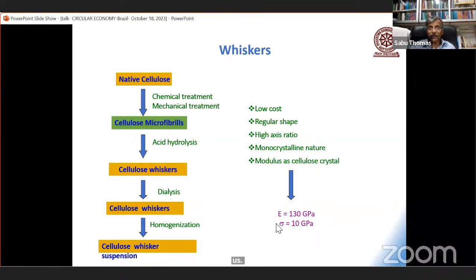Look at the tensile strength of the material. The tensile strength of the material is 10 gigapascal, and the modulus is 130 gigapascal. And these materials have lots of advantages: low density, regular shape, high aspect ratio, monocrystalline,